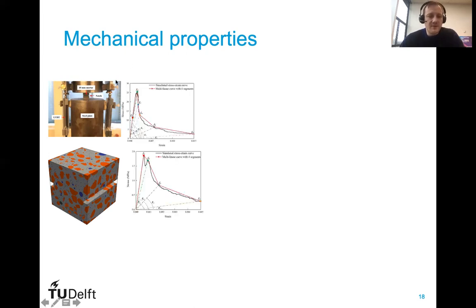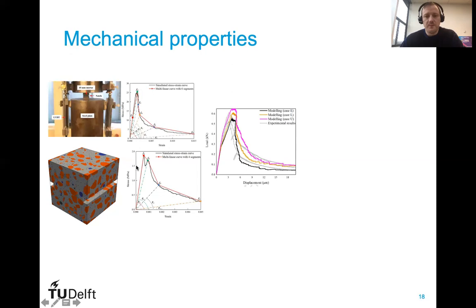As I said, from the smaller scale, we have the properties of the cement paste, shown here in black, which we then discretize in a multilinear way and assign to the cement paste elements, which are here in gray. And we do the same for the ITZ elements. We also have calculation results from the smaller scale. We discretize these results and put them into the interfaces.